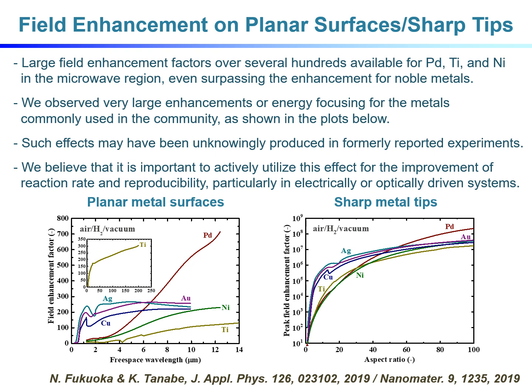Next, we calculated the field enhancement factors on planar metal surfaces and sharp tips. As seen in these plots, surprisingly, we found for planar surfaces that large field enhancement factors over several hundreds are available for palladium, titanium, and nickel in the microwave regime, even surpassing the enhancement for noble metals. Conventionally, plasmonics has been discussed mainly for noble metals, and our result was actually a new finding for a wide range of the hydrogen energy field.